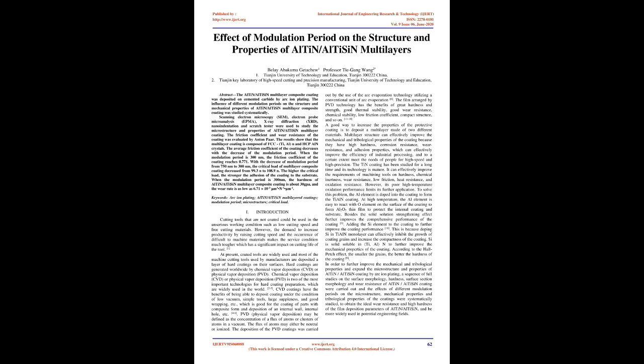Effect of modulation period on the structure and properties of AlTiN/AlTiSiN multilayers. Abstract: the AlTiN/AlTiSiN multilayer composite coating was deposited on cemented carbide by arc ion plating. The influence of different modulation periods on the structure and mechanical properties of AlTiN/AlTiSiN multilayer composite coating was studied systematically.